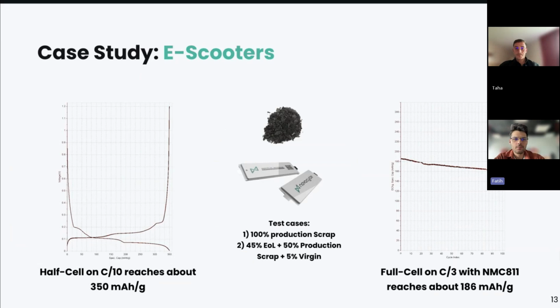So we took the anode from different batches. We actually had 3 test cases. I think the third one is not here. So there's a production scrap, different mixtures, and just end-of-life batteries. And the usual trend with the material that we recovered: on the left side, we see a half cell test with the recovered or recycled anode material in a C10 test. And we see that the initial capacity reached up to 350 milliampere hours per gram, which is quite comparable to virgin anode materials.